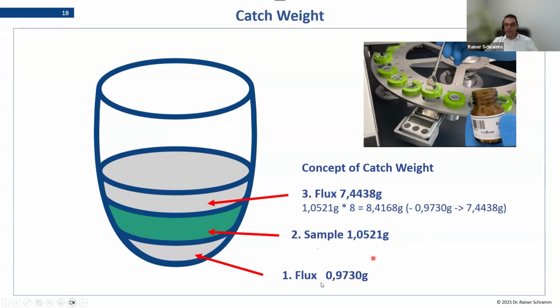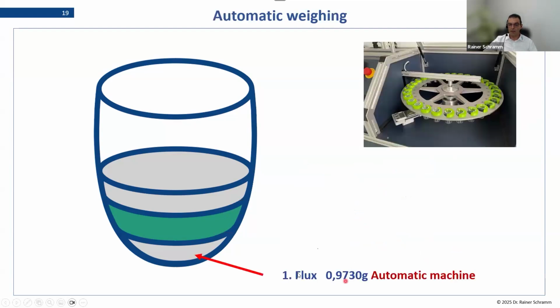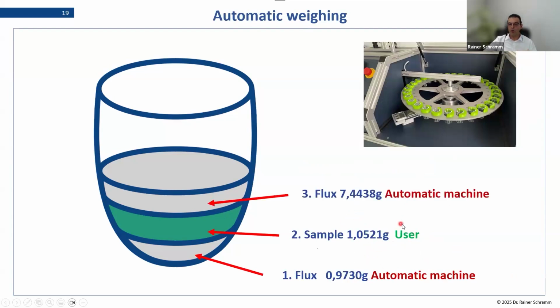So the concept is: first dose a bit of flux, then the sample by the user, and then complete the flux dosage so that the dilution factor is exactly 8. So in reality, the machine is doing the first layer of flux, then the user is adding the sample, and then the machine completes the job. And this you can do for up to 30 samples in total.